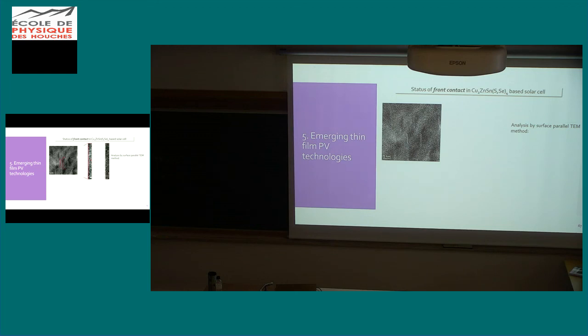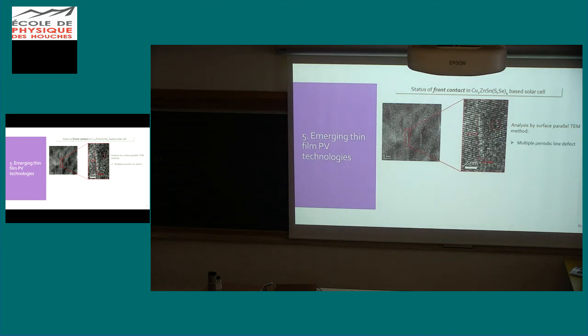Okay, I will accelerate, it's just the end part. So we observe a lot of defects, linear defects and point defects, at the surface of CZTS. And all these defects, of course, can be dislocations or some subgrain boundaries.